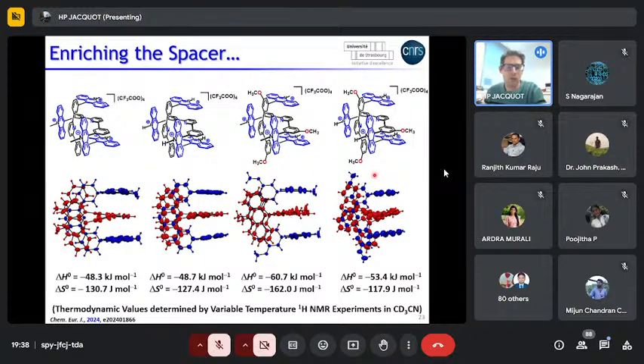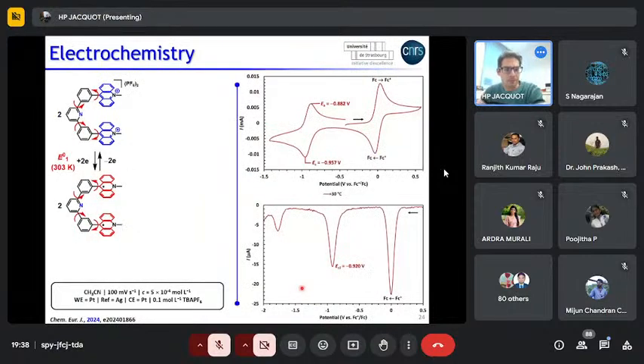So these two molecules also crystallize in their dimeric form. And now when you compare the thermodynamic parameters, you have an increase of the enthalpy contribution, meaning that you stabilize the system by weak interactions. So this goes for some pi donor, pi acceptor interactions. This was also confirmed by electrochemistry.